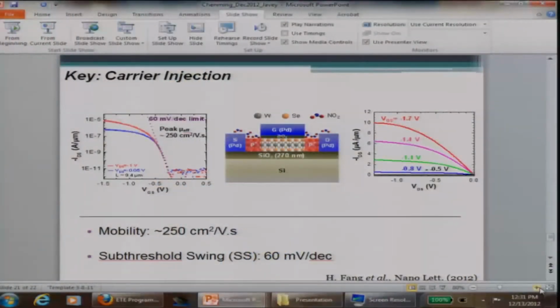And if you do that, then you get these beautiful transfer characteristics. Subthreshold swing is 60 millivolt per decade. It's a single monolayer. There are no dangling bonds. You get the ideal limit right away. The mobility is 250 centimeters squared per volt second, which is, again, pretty good for that particular thickness. And you get very nice IV characteristics as well, output characteristics as well.